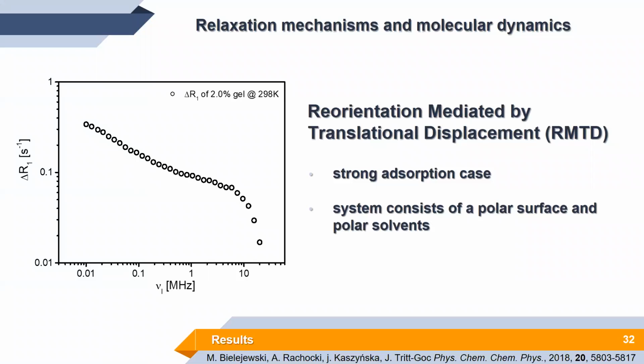And what it actually makes. When we imagine, let's say, a single molecule of the diffusing solvent, which is adsorbed at the surface of the gelator matrix, because of the strong adsorption, its orientation is somehow predefined by the surface at which it is adsorbed. And because the surface is not regular, it's not flat, but is very irregular, when in time the molecule travels on the surface, the predefined orientation of the spins in the molecules is changing in time when it's moved from a point to another point on the matrix.